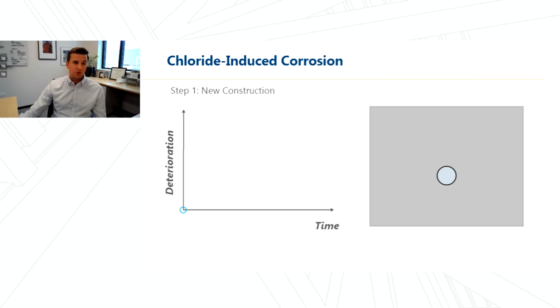Let's assume that at new construction, we didn't batch in any chlorides, so we have chloride-free concrete, but it's in an environment where there is a surface exposure to chlorides. Over time, those chlorides will diffuse from the surface exposure in towards the region of lower ion concentration, and they will continue to diffuse, and eventually the chloride ions will reach the depth of the steel. When they build up in sufficient concentration at the depth of the steel, that can depassivate the steel and corrosion can initiate.